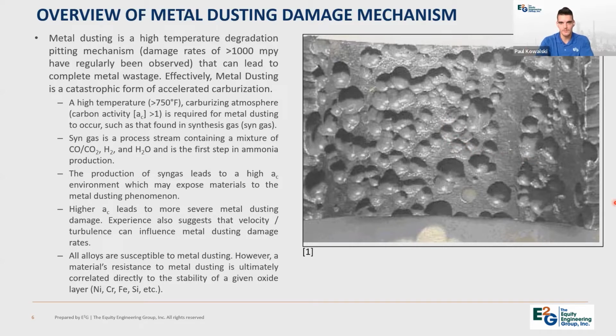So kind of the common factors or requirements for this mechanism to occur, again, high temperature, typically 750 degrees Fahrenheit or higher, as well as a carburizing atmosphere, which is defined as having a carbon activity higher than 1. This high temperature carburizing atmosphere is commonly found in the syngas loop, which is the first step in ammonia production, as this syngas stream contains carbon monoxide, carbon dioxide, hydrogen, and steam.